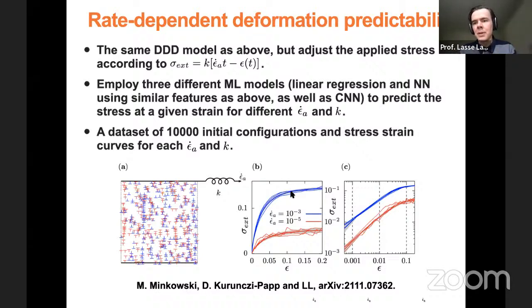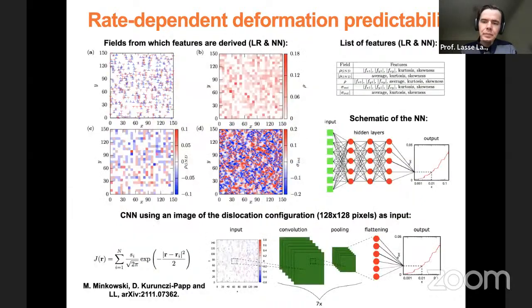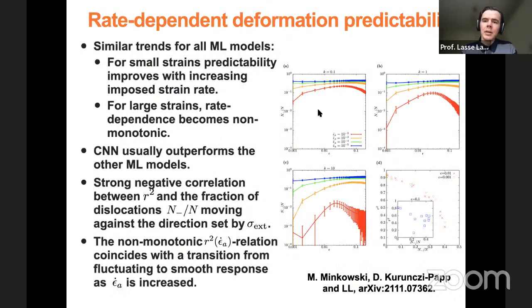And now there are two kinds of stresses in your system. So this external stress that we show here, and then the internal stresses that are, roughly speaking, constant. But now, because of this rate effect, the external stress will become, in relative terms, more important for large strain rates, which then shows up as, here what we do is we look at the fraction of dislocations that are moving against the direction of the externally imposed stress.